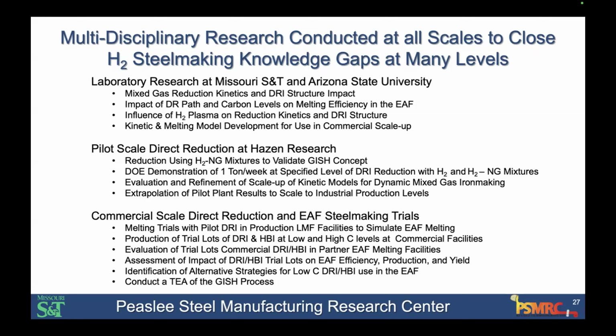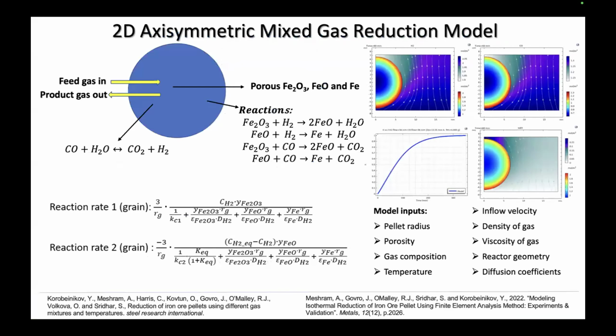For the pilot scale part of this, we constructed a DRI reactor that is capable of producing about 2.5 tons a week, to produce enough DRI based on hydrogen and mixed gas that we can evaluate its melting behavior in a production environment. And then finally, we've done full-scale production trials in the plant environment to produce DRI at commercial DRI production sites with low and high carbon, but also to melt these materials in various production facilities.